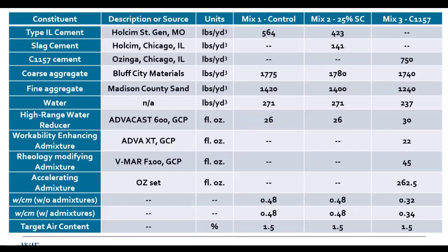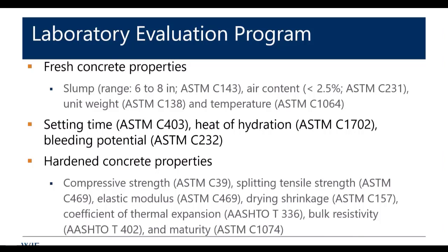The big things to take away here are the cement contents on that number 3 mix that was higher, but also notice the amount of workability enhancing admixture that we used with that 3rd mix. So it did require a bit extra admixture to achieve the workability that we were looking for. We were looking for a pumpable concrete, so we're looking at fairly high 6 to 8 inch slumps. Air contents less than 2.5%, and then unit weights and temperature were measured.